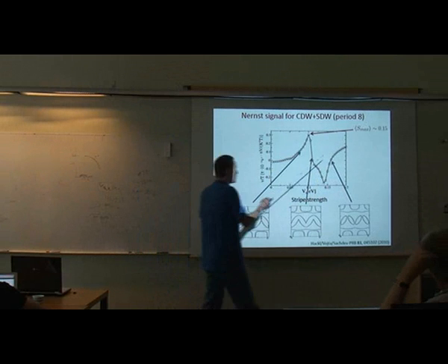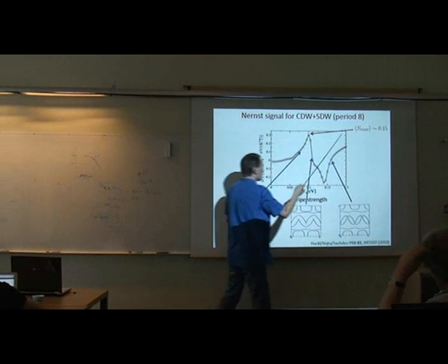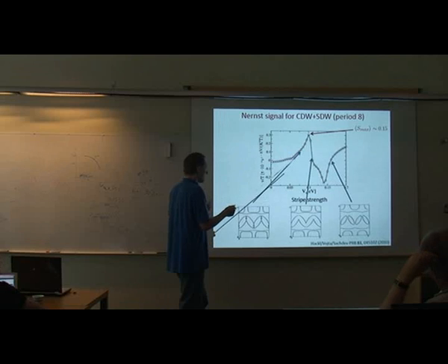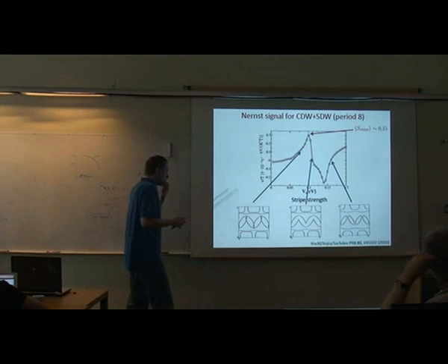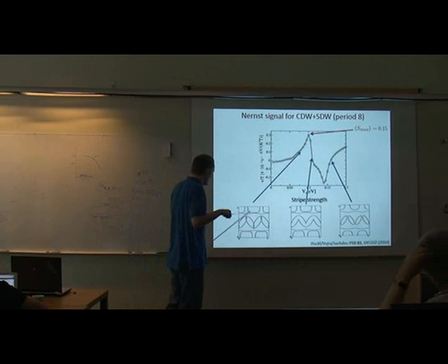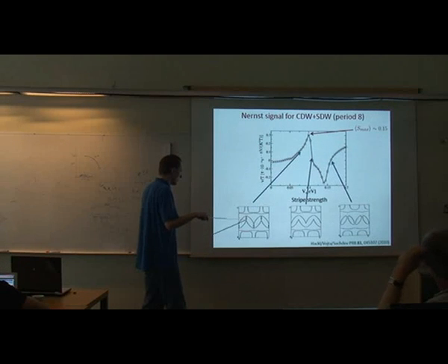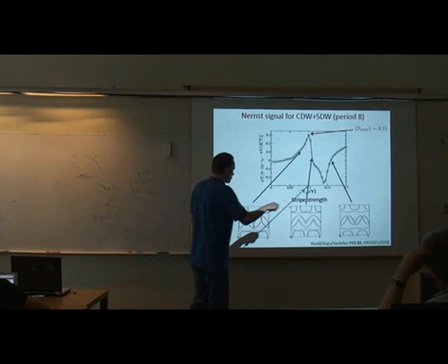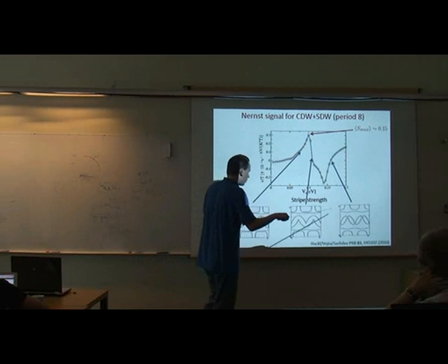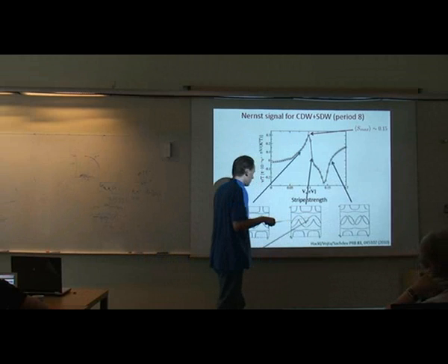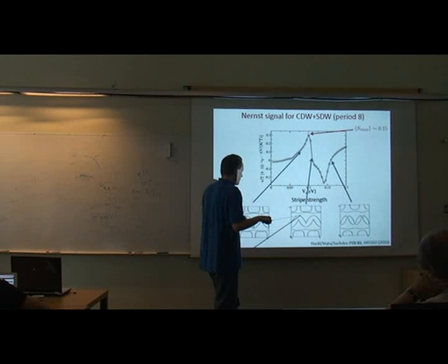The maximum moment you see is 0.15 roughly in these materials, once you are very close to 1/8 doping. And what you see here are particular electron pockets. These are very small electron pockets. And once you change this potential strength, you essentially erase first these electron pockets, and then you form hole pockets here by fusing these open orbits.